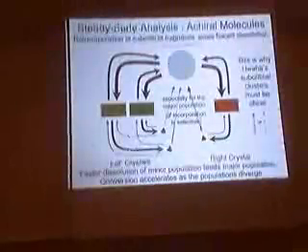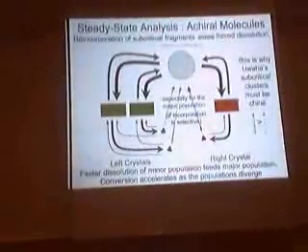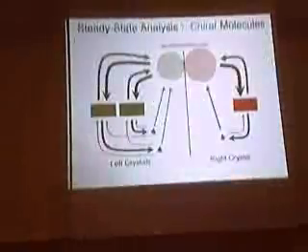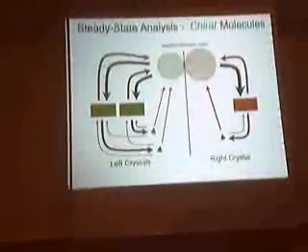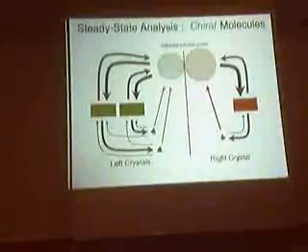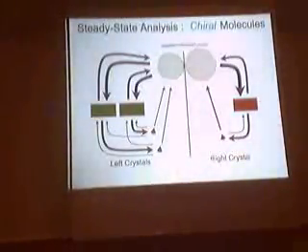Yeah. What I did is I started in the solution with my compound, the molecule, which is racemic, of course, without base. Yes. So then you have a steady conglomerate. Yeah, that's this. And in the solid, we have 80% of the left-handed crystals and 20% of the right-handed crystals, maybe even more enantiomeric excess. And, well, we wait, we measure the enantiomeric excess of the solution, which is completely racemic, and of the solid, which is 80% or so. And then we start grinding for about a week or so.